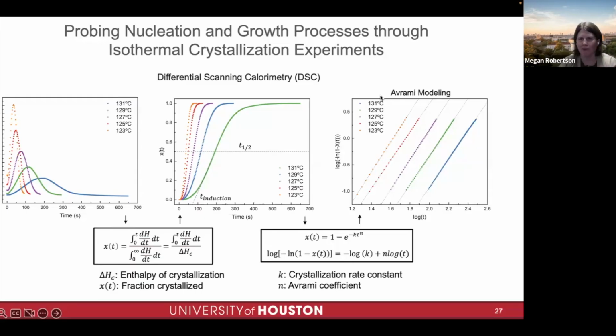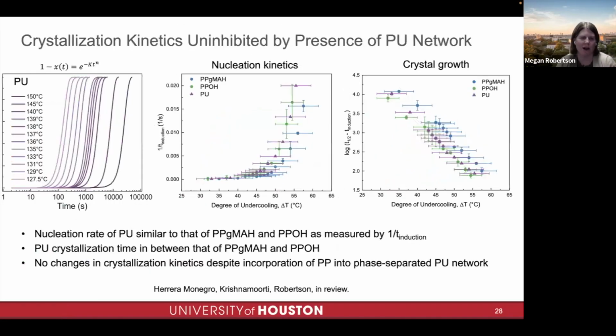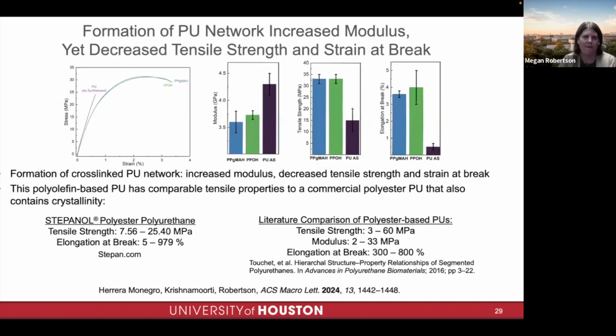And we can use an Avrami process to model this data. But the take-home message here is from all of this data and its analysis, we can look at both the nucleation rate and also the crystal growth rate. And again, comparing across our three materials, even though we are bringing polypropylene into this network, it is undergoing crystallization kinetics just like it did for the neat polypropylene.